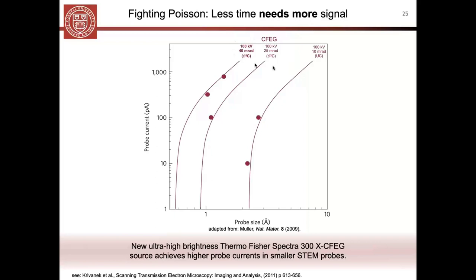And so if you look historically, this is data from about 10 years ago on a cold FEG, you can see that aberration correction has had a huge impact on being able to push this limitation. So as you go from an uncorrected instrument here at 100 kV, once you introduce aberration correction, you can start to open up that C2 aperture, the condenser aperture, the probe forming aperture, as you move up to higher orders of correction. So here we've gone from 10 to a 40 milliradian probe convergence. And so that already really allows you to increase the number of electrons that you're putting through your sample, while at the same time actually decreasing the size of your probe. So now, most of these really high resolution instruments are fifth order corrected. And so what's the next step to keep pushing us to the left of this diagram?